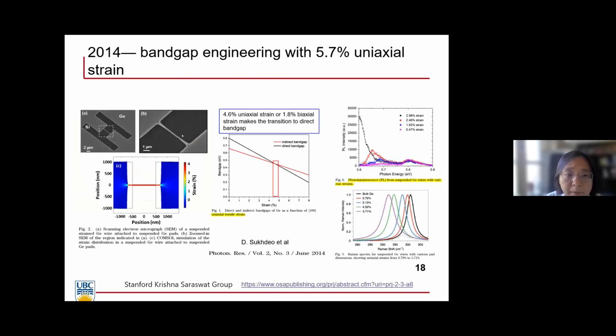And of course, if we make germanium into a tiny bridge, we can have all this tensile strain be concentrated. So that's a stress concentration method. And really, we can put huge uniaxial strain on it. And if that happens, we'll see the direct band gap, the black line, keep shrinking faster than the indirect as tensile strain goes up. So at one point, germanium is going to become a truly direct band gap material. So that's with high uniaxial tensile strain.